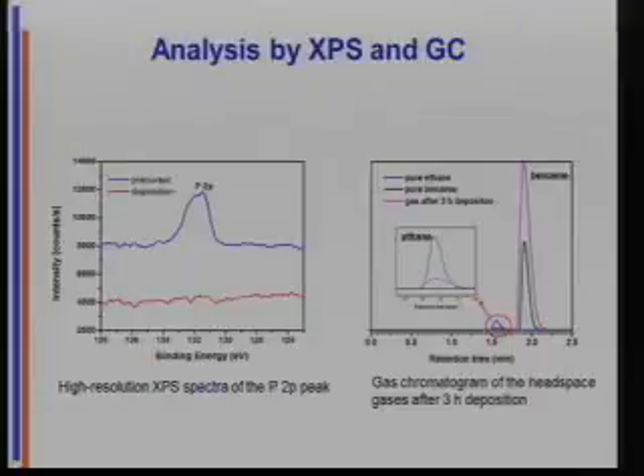Now, what's really cool about these is whenever you make nanoparticles in solution, you have to control the aggregation. And it's controlled by surfactants or it's controlled by halide ions. And so when you make colloidal gold in solution, its surface is covered with stuff. And if you want to use those nanoparticles for catalysis, for SERS, for anything, you've got to get the stuff off of them or wait for it to dissociate. These nanoparticles are clean. What could be on them?